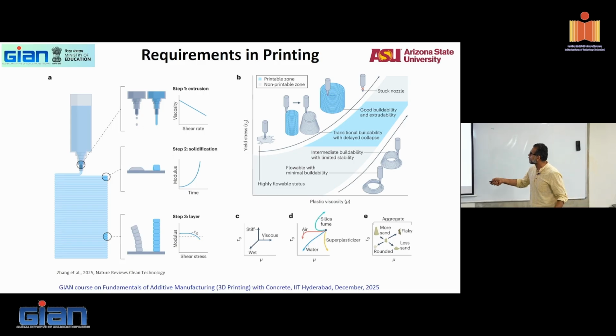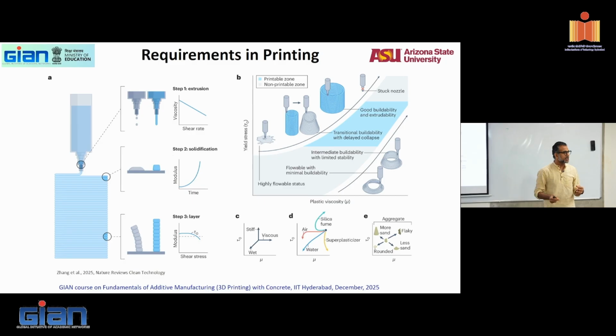So I want to get to a point where the mix is not too stiff, yield stress is not very high. The mix is not too wet, viscosity is not very high. I want to be in a zone where there is enough yield stress and there is enough viscosity. There is enough yield stress to initiate flow. There is enough viscosity to keep flowing. Correct? So that is your impossible condition that we have to satisfy. Not impossible, we can. So that's the intermediate buildability condition.